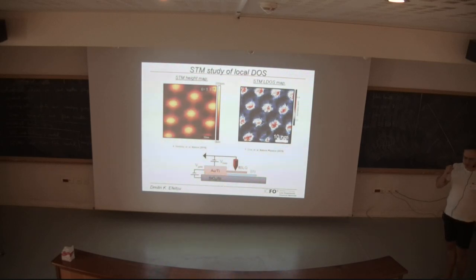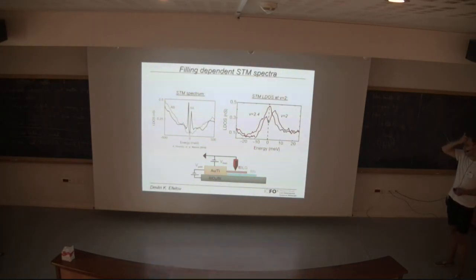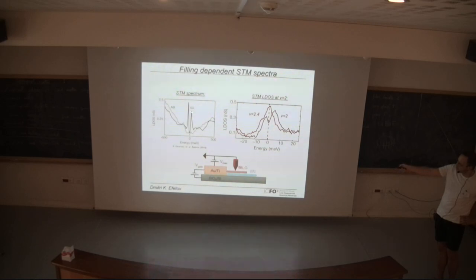What they can do now is also apply a gate. Just as we do in transport, they can apply a gate, sit at the AA lattice site here, and look at how the spectrum changes. This is a typical result they get. This is, again, local density of states as a function of energy, and usually the blue curve is the result people obtain in several experiments right now. They obtain a really high density of states in the Van Hove singularities, which are created by the flat bands. Each of those peaks here is basically the extremely high density of states which arises in each flat band, in the valence and the conduction band.